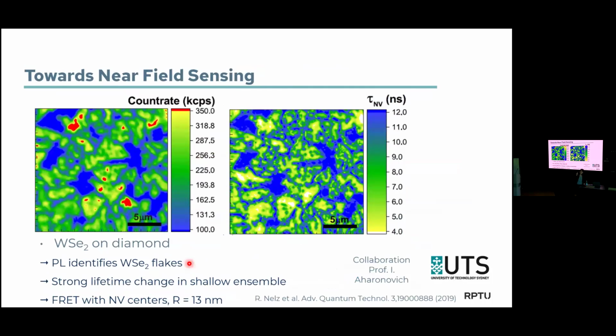Okay. And then in this case, we did the addressing by scanning our laser over the sample. Okay. So you bring it close by bringing it on the surface and then you scan the sample. In this case, you can't use the microwaves, of course, because they don't do local addressing. No, the microwave in this case doesn't do local addressing. I mean, we have the microwave here, but of course it addresses the NV centers in the whole region. Yeah, exactly.